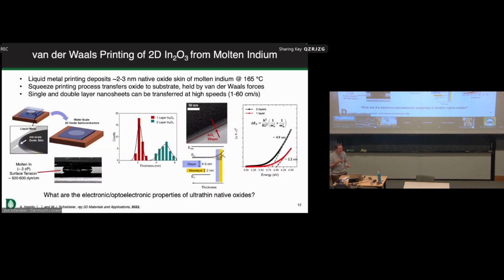So our model system for understanding 2D oxides was indium oxide. Indium oxide's essentially one of the most important materials for display electronics, for transparent conductors in energy applications. And indium is also a rather unique metal in that it has a low melting temperature. It's just 157 degrees C. So you can have indium in the molten phase at temperatures that are highly compatible with any plastic we would like to transfer it to.